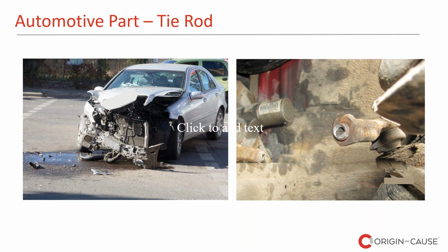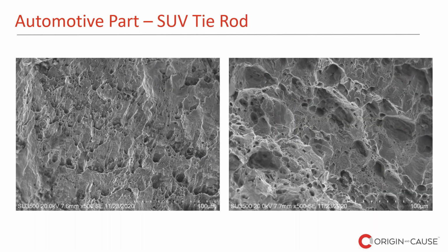Tie rod is a very important piece of equipment in a vehicle because it connects the steering wheel with the wheel. So the tie rod broke, as you can see on the right side, the image. And again, we took it under the scanning electron microscope and we looked at the fracture surface. It must be told that fracture surfaces are actually telltale stories. They contain, if properly preserved, features which are indicating what was the failure mode.